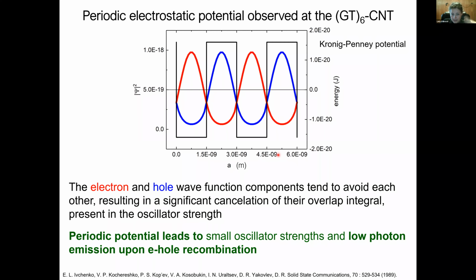And what we find with these physics-based models is that if you have a periodic potential, the electron and hole wave functions will avoid each other. And that will result in a significant cancellation of their overlap, which will affect the oscillator strength. And eventually, the small oscillator strengths are going to lead to low light emission upon exciton relaxation. So basically, we were able to show with a simple physics-based model that if there is a periodic potential present where the exciton exists, then we expect the nanotube not to emit light. So that's the conclusion coming out from classical modeling.